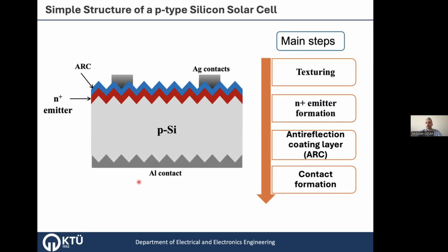These are screen printed contacts, dried, and afterwards they are fired. After the firing, you have the contact on the front side, and with the aluminum-silicon alloy, you have the P+ BSF layer on the backside.